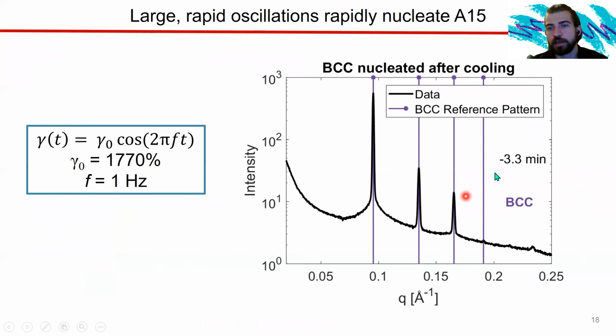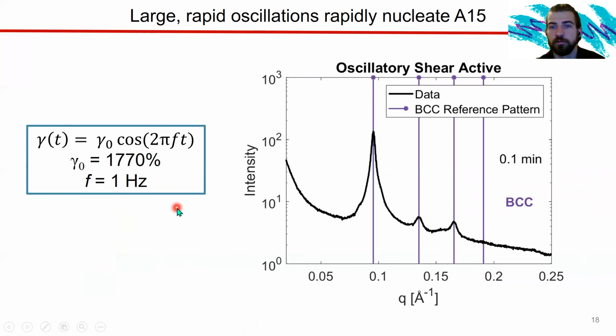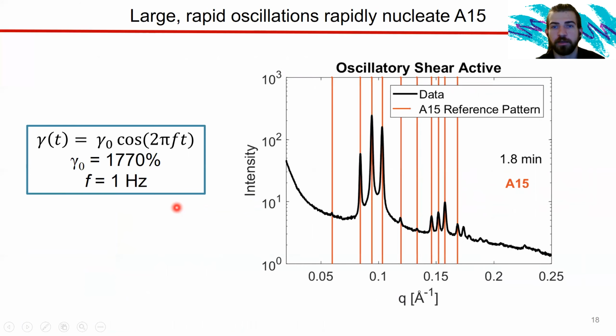So you can see this is counting down. We're going to apply oscillatory shear at 0 minutes. All right, and you can see that the sample rapidly changed to an A15 phase in a matter of about 1 or 2 minutes. Now that's a drastic change from 5 months. I'm just going to let this roll over and play again. And you can see that as we approach 20 minutes, the Frank-Caspar A15 phase is pretty happy.